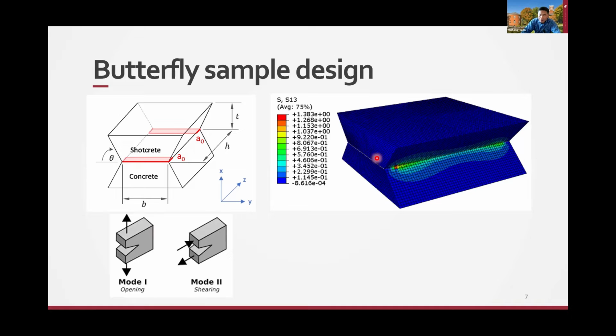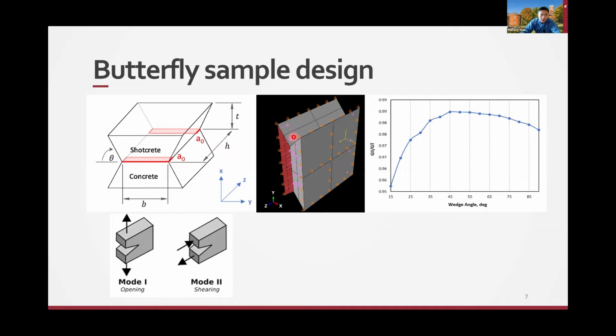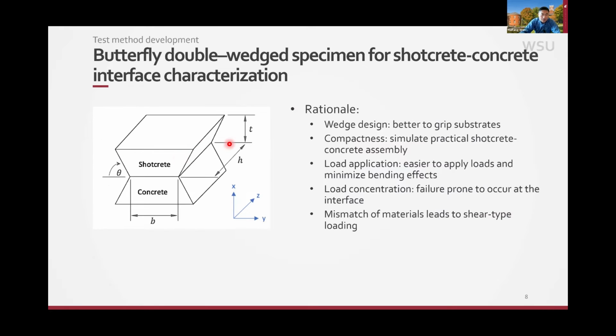This is based on the finite element test. The design angle was determined to be 45 degrees, based on the finite element results. That's the angle you see here, the 45-degree angle. The advantage of using this butterfly test sample is, number one, it grips better. Because you have this wedge here, compared to a cylinder sample, which typically you have to anchor, this one you can use the friction and the support from the wedge to pull the sample, so it grips the material better.